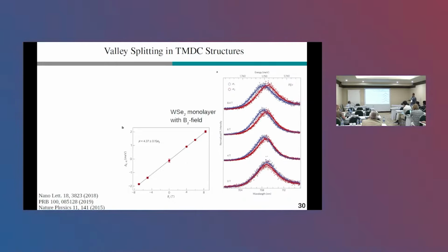Once you crank up the external magnetic field in the out of plane direction, you will find such a very nice splitting of these 2 peaks, which is known as the valley splitting. And this valley splitting follows this linear trace as function of the magnetic field, where also the g factor plays a heavy role. In this case of bare monolayer TMDCs, this g factor value is around 4. But still, if you apply a magnetic field of 8 Tesla, you get only a valley splitting of 2 millielectron volts. And this is where the proximity physics comes into play.